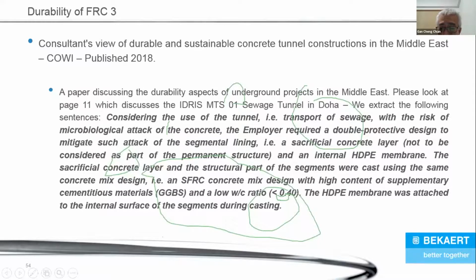it requires the transport of sewage with the risk of microbiological attack of the concrete. Hence, the employer requires a double protective design to mitigate such attack of the segmental lining: a sacrificial concrete layer not to be considered as part of the permanent structure, and an internal HDPE membrane. The sacrificial concrete layer and the structural part of the segments were cast using the same concrete mix design. And that concrete mix design is a steel fiber reinforced concrete mix design with high content of supplementary cementitious material, GGBS, and a low water cement ratio, less than 0.4.